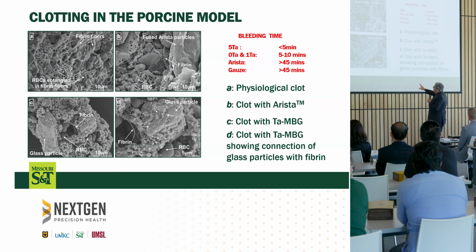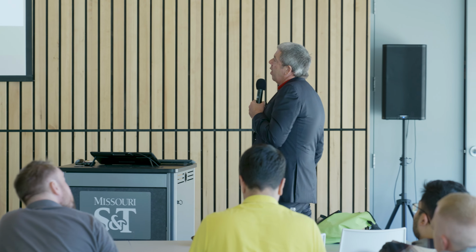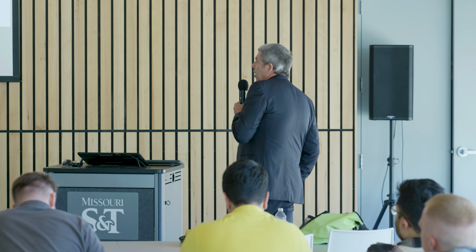When you look at our material here, and this is probably the best two examples I could find, we see the same fibrin chains, we see the same red blood cells, but we see them spreading out and growing on the surface of our glass particles. So they're reacting with the material, and the material is actively facilitating the clotting to occur.